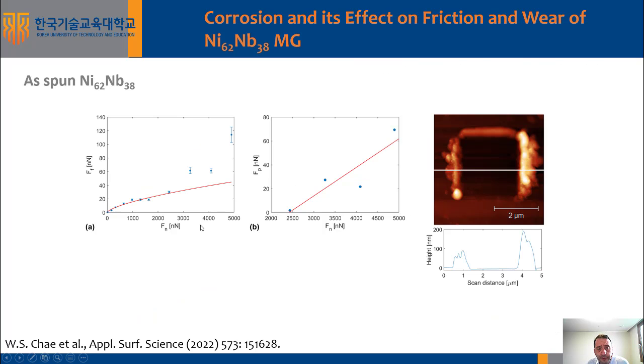So before immersion in acid, we measured the ribbon surface by friction force microscopy to do our friction and wear measurements, and we observed that we had a significant amount of abrasion. The shear strength deduced from this fitting was around 1 gigapascal, so that corresponds to the shear value, or the necessary stress to shear off an asperity between tip and surface.